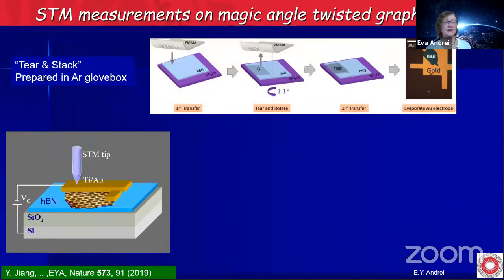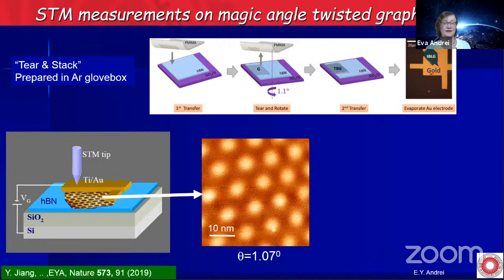As we did. So we said, okay, let's see. Our question is: is it? We could not go to very low temperature with STM to see the superconducting gap, but we could be a little bit above the superconducting gap and ask questions about the nematic phase and the pseudo-gap phase. So we prepared a sample with the tear and stack technique, put it in our STM, protected from the bottom with boron nitride, and looked at it.